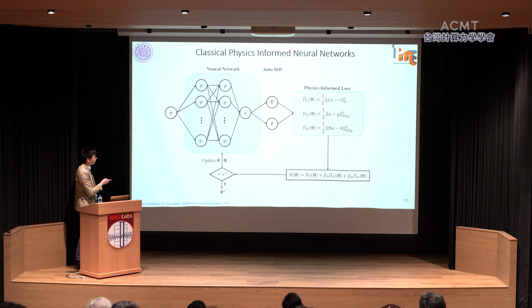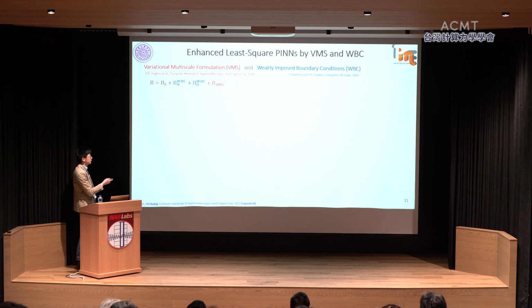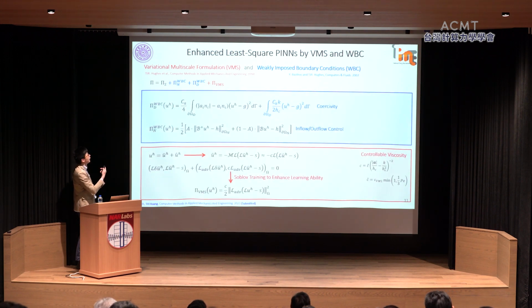If you're really modeling the fluid problem, you'll find out that not all the schemes really converge. So to enhance it, I revisited the two famous schemes by Hughes, the VMS and WBC, the weakly imposed boundary condition. The idea is, although I use a least square type functional, I can design a least square functional that is similar to the weakly imposed boundary condition to impose coercivity, and to impose different regularization on the inflow and outflow boundary. And for the formulation shown here, if you take a variation, it will degenerate to the WBC formulation.